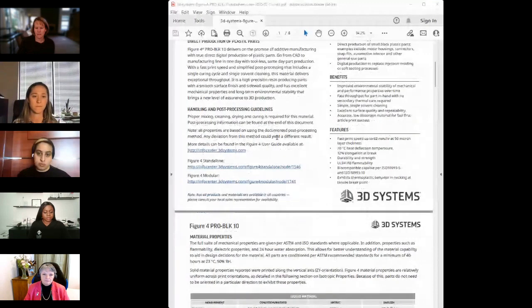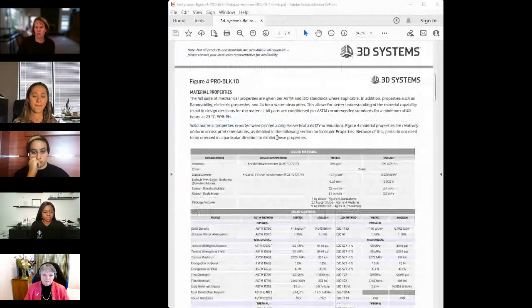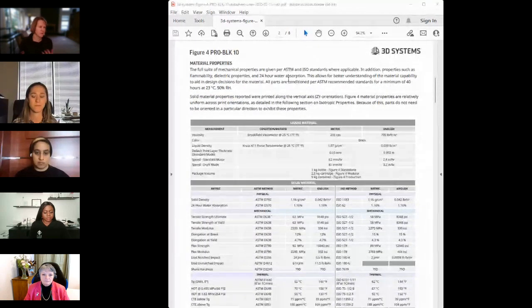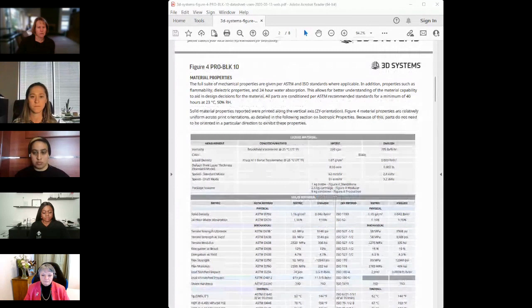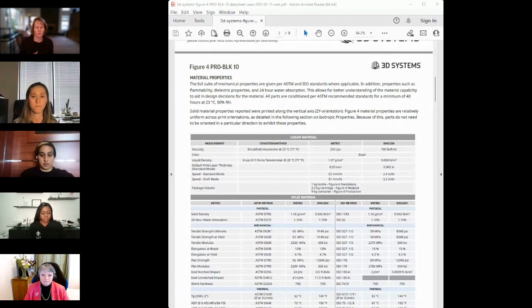So the first section of our data sheet is just a whole bunch of material properties. And this is pretty similar to what we've done for a long time. We show a wide variety of metrics that engineers might need to understand in order to choose the right material for their job. We publish both ASTM and ISO standards because, in different industries, different standards are more important. And then as we create the numbers that go in here, we typically test 3 sets of samples for each metric. That might be 3 different lots of material or printing on different printers. And we do our best to follow the standards.